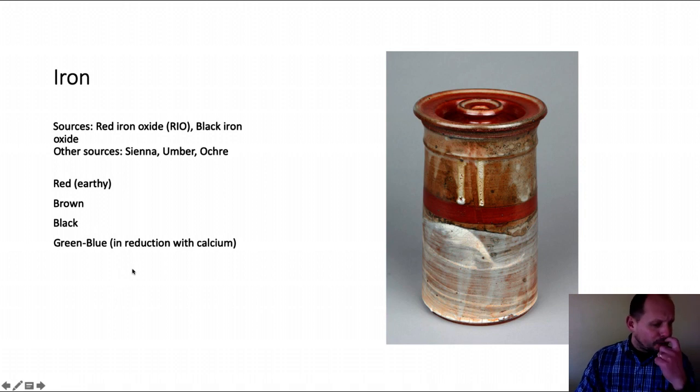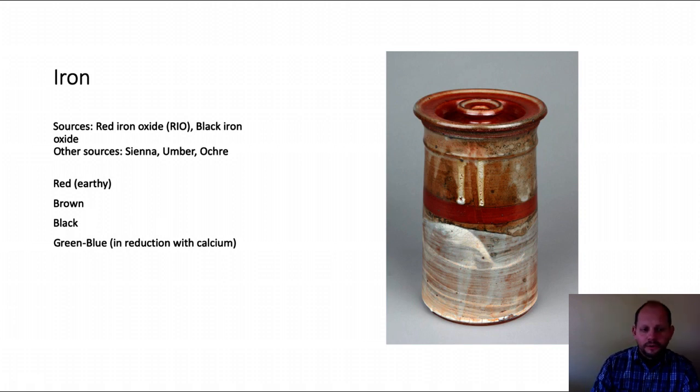There are other glazes called celadons. Again, it's another Asian glaze. Celadons are a Korean glaze. With trace elements of iron, you'll tend to favor green to blue hues, in glazes that are favored with calcium. And then the less iron content you have in those glazes, the more blue it will present, and with more amounts of iron, it will favor green.